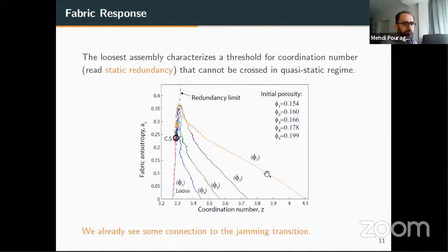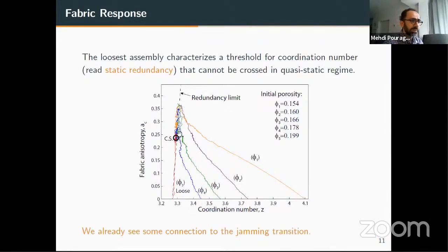We start looking at that by looking at different initial states, and we see that almost for all of these states, the micromechanical state of the sample approaches the same line. It stays on the same line when it reaches it, and then it goes to the critical state at the end. And it seems that this line is a sort of threshold for coordination number that cannot be crossed in quasi-static simulations. Remember that coordination number is related to static redundancy. So static redundancy is being decreased. There seems to be a minimum limit for static redundancy, beyond which we appear to have no static equilibrium. And we already see some connotations with jamming transitions, because jamming transition has also been related to static redundancy.